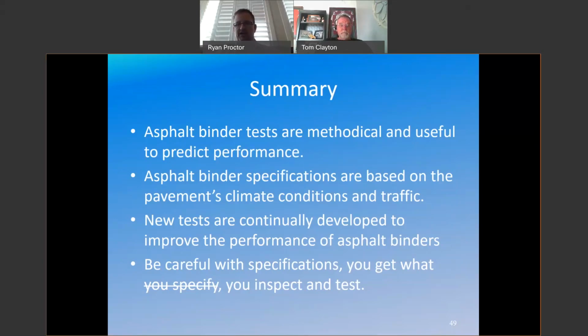The asphalt binder specs are based on the climate and traffic. It's very important to understand that. I would also add to that there's a reason we do them in 6-degree increments, and that's because it's not really feasible to have a hot mix plant with 8 tanks for binder if it's a small plant, or a specialty plant that might have 16 different tanks in place. It's always nice to think about other binder grades that we could use, but it's not always that simple just to add them. We're always looking at new tests.